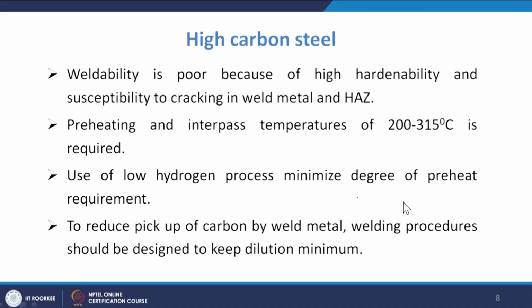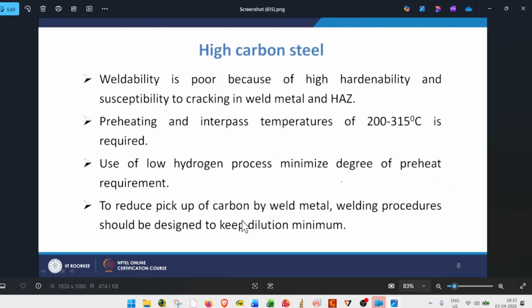Okay, next coming to the high carbon steels. So high carbon steels generally have poor weldability, as we have seen. If the carbon content is increasing, hardenability increases and martensitic formation is more. So to prevent that, if the carbon content is increasing, the preheat treatment requirement and its temperatures also increase. In this case the preheat treatment requirement is 200 to 315, whereas in case of medium carbon steel it is 100 to 150 to 200 degrees.